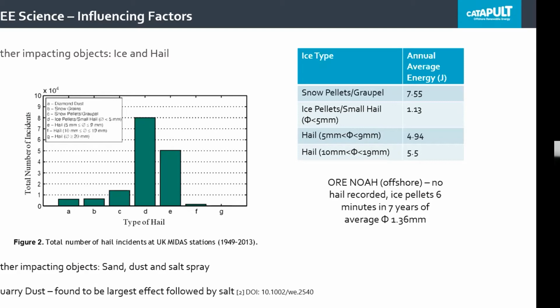He then converted the number of events onto a wind turbine to calculate the average annual energy. And what you can see is that the most frequent ice pellets or small hail actually has the lowest annual average energy. It's not until you get to the slightly larger hail sizes that you're increasing in intensity, but this is still well below the intensity that is actually occurring from your rain impacts.